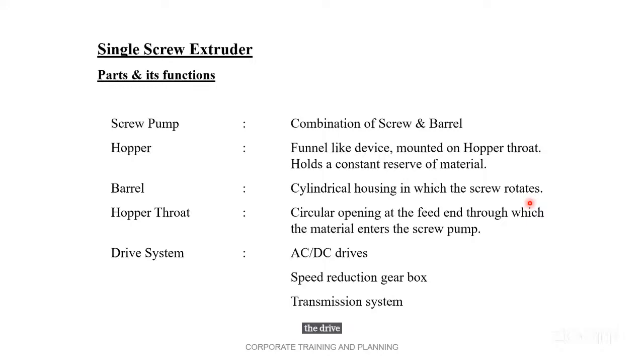The drive, AC DC drive, I told you yesterday only. Speed reduction gearbox. We have a motor which has a speed of more than 1000 RPM. Therefore, we have to use a drive system to reduce such a speed. Generally, we use speeds of maybe up to 120, 130 RPM for a single screw extruder. Therefore, the transmission system from the rear side of the extruder is very important. We have to reduce the speed of the screw from 1000 to 100 RPM, and that is possible only by using the gearbox and transmission system.